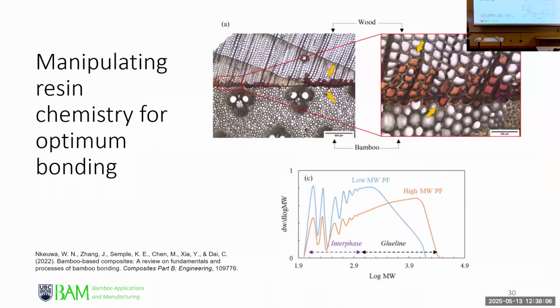And also difficult in terms of glue penetration. You can see from this example, on top is the wood, the bottom is bamboo. The same glue applied, the PF glue applied, you can see how glue can easily migrate from the surface, the interface to the inner cell, whereas almost nothing can go through bamboo. So there's real requirement in terms of the treatment of bamboo and how the glue is applied.